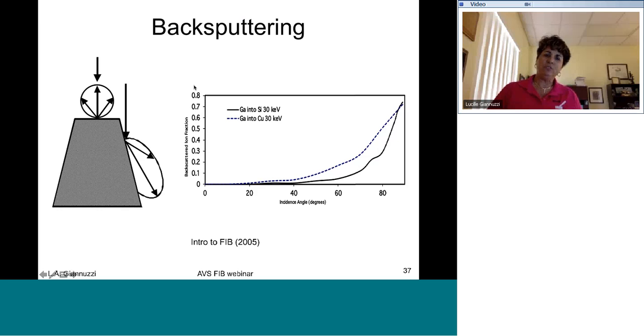Back sputtering, this is important to know because this will tell you if you've got redeposited material, particularly on your TEM sample. If you hit your material normal to the surface, sputtering will come off in a cosine distribution, and the back sputtering will increase with incident angle. Up to almost 75 to 80% of the incoming gallium will be back sputtered at these high incident angles, whereas at normal incidence, basically almost zero gallium will be back sputtered.